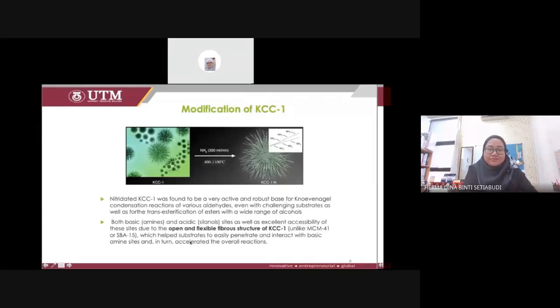this catalyst can help the substrates to easily penetrate and interact with the basic amine site, and in turn accelerate the overall reaction. This is they compared with the MCM41, or conventional MCM41, or SBA15, and they found that KCC1 showed the superior one compared to both of these silica catalysts.